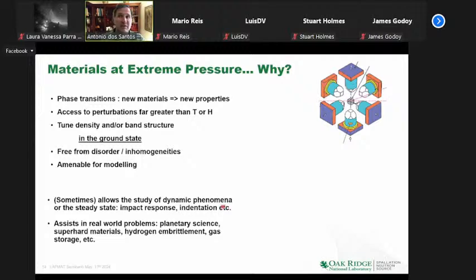There's clearly the field of shock physics, response to impact on glasses and other structural materials. Studies on indentation have found new materials in silicon and germanium. This is clearly not pressure, but it's pressure adjacent, and it also assists in real world problems like planetary science, ice clathrates at the bottom of the ocean, the development of new super hard materials, the consequence of hydrogen embrittlement, which is important for the hydrogen economy, and improved gas storage. So there are a lot of areas, and you start seeing here already that pressure is basically many things. You don't have to be at 100 GPa all the time. A few kilobars in an application for society can already be fairly high pressure.